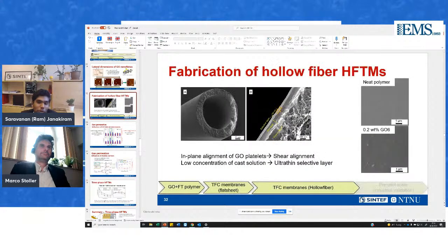In that case, what I wanted to say is that we have a solution which is very, very lean, and we are making a system where the film is 192 or 200 nanometers, which is basically very little polymer. In that polymer, you have 10 weight percent of ionic liquids, and the graphene oxide is 0.2 weight percent. So technically, the most expensive components of this system are graphene oxide and ionic liquid, at 10% and 0.2%. And the amount of polymer you need for a 200 nanometer film is very, very small, which means that you can make huge amounts of modules with very little money. So from a design perspective, it makes sense.